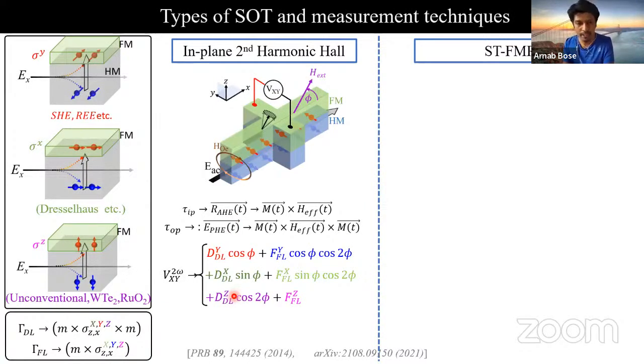That is what we experimentally measure. And by fitting Hall voltage with these expressions, we can identify and quantify all 6 different types of torques, because there are 6 parameters to fit. Note that here we do the experiment for different magnitudes of the field, and by changing the magnitude of the field, we get the dependence of this coefficient, and from that we can distinguish whether the generated second harmonic Hall voltage is related to spin orbit torque or a thermal effect.